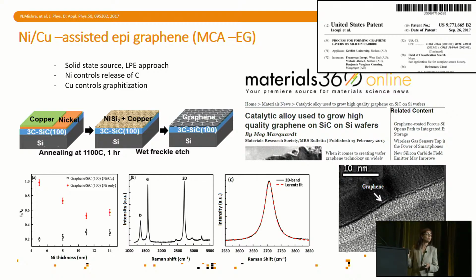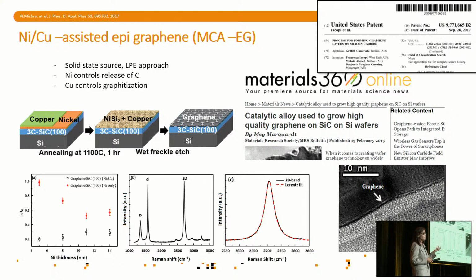However, nickel alone doesn't really work well. And you can see that from here, where this is the ID over IG, an indication of how many defects are in that layer of graphene, versus the thickness of the layer. And you can see that nickel tends to have a lot of defects. So nickel alone had been used before, but it wasn't that attractive. Then this trick had been used before for semiconductor nanowires or even for carbon nanotubes.